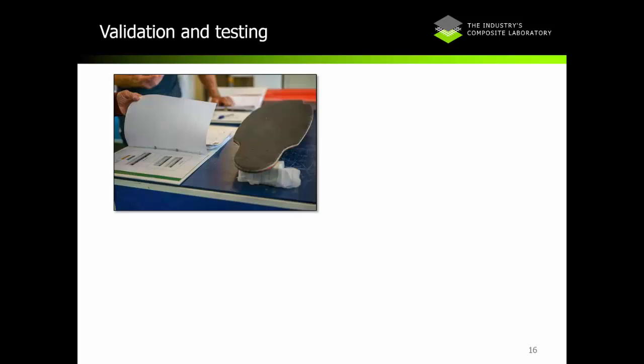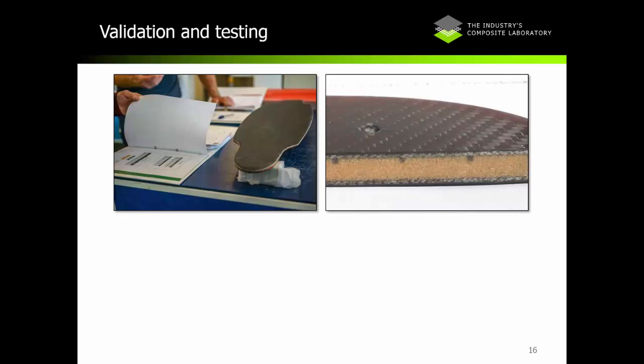So we measured the bending stiffness of the board. We made a few boards, and we cut a cross-section out of one of them. Here you can see the PET foam core, and you can see the flax fibers, which are the lighter color fibers here. And you can see the carbon fiber. I'll also mention that with the flax fiber we had the fiber orientation at plus and minus 45 degrees. This gave torsional stiffness to the board, which is also important. So not only is the flax dampening vibrations, it's also giving us some torsional stiffness.